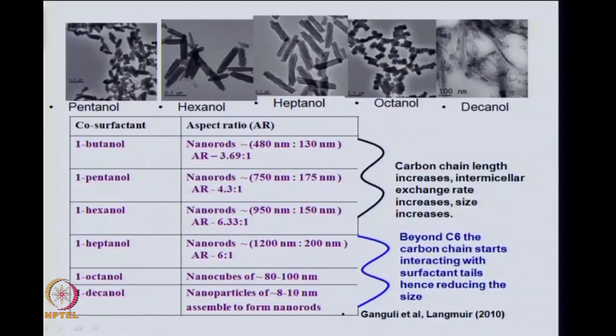So, you start with 5 carbon, 6 carbon, 7 carbon, 8 carbon and 10 carbon, and up till say 6 or 7 you see the anisotropy, and beyond that you see they become more uniform particles. And we have tried to explain that beyond C6 the carbon chain in the co-surfactant starts interacting with the surfactant tails, because the co-surfactant tails are hydrophobic and the surfactant tails are also hydrophobic, and they start interacting with each other, and hence it decreases the intermicellar exchange, and hence it reduces the size of the particles which are formed.